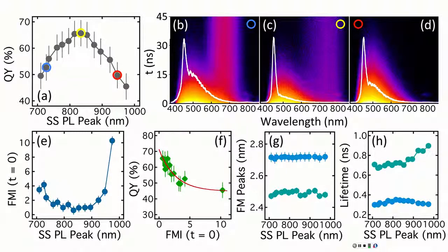It's just going to be really fast, and that's what you're going to see, and then it's dark. And if you focus only on 600 to 800, it will be different. There will be several kinds of decays. At 700 to 800, you're probably going to see just two: one with about 10 nanoseconds, and one with 1 to 100 microseconds.